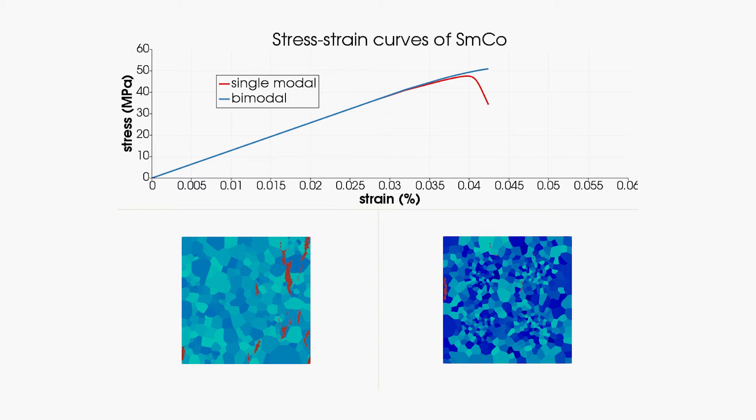But in the new version, the clusters of fine grains make the cracks break up and dissipate their energy.